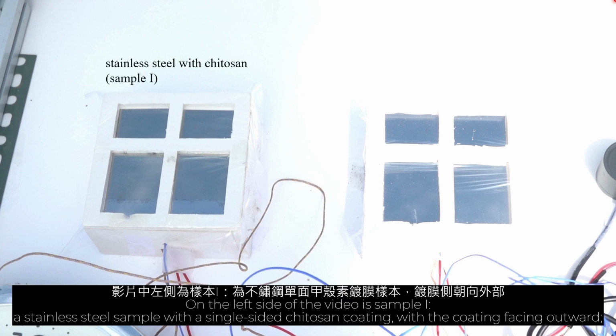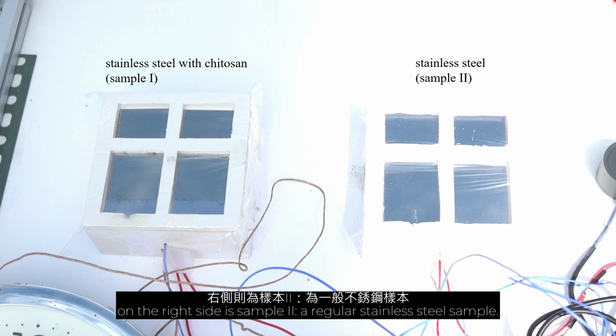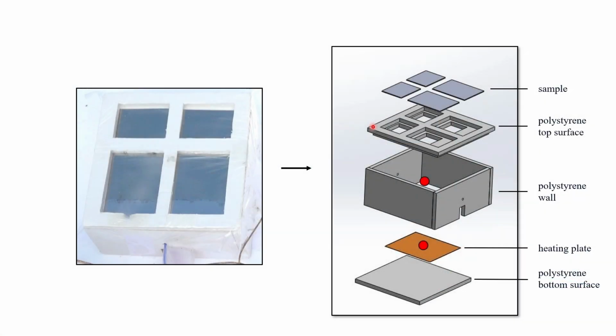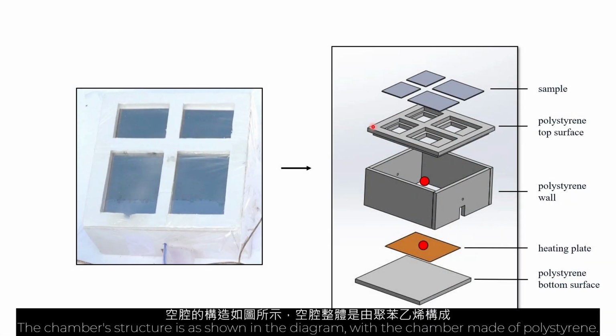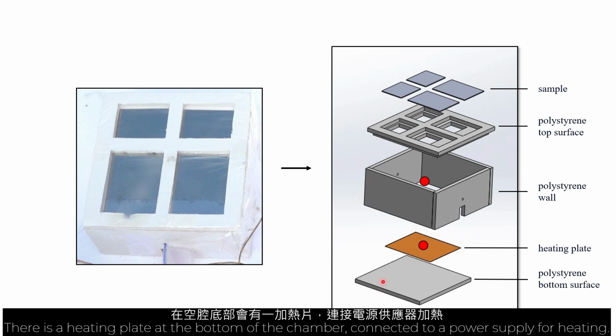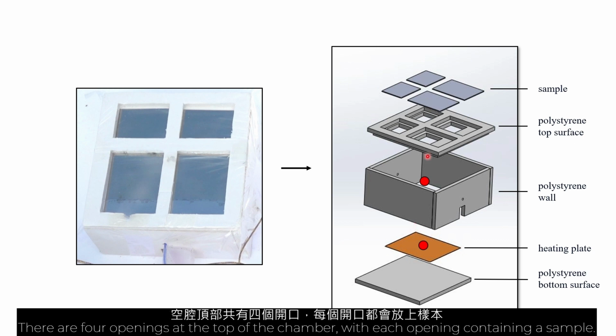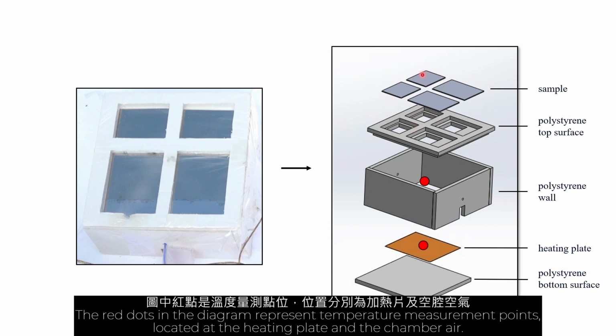On the left side of the video is sample 1, a stainless steel sample with a single-sided chitosan coating, with the coating facing outward. On the right side is sample 2, a regular stainless steel sample. The chamber's structure is as shown in the diagram, with the chamber made of polystyrene. There is a heating plate at the bottom of the chamber, connected to a power supply for heating. There are 4 openings at the top of the chamber, with each opening containing a sample. The red dots in the diagram represent temperature measurement points, located at the heating plate and the chamber air.